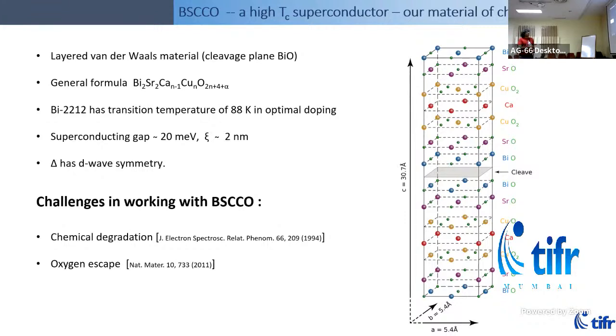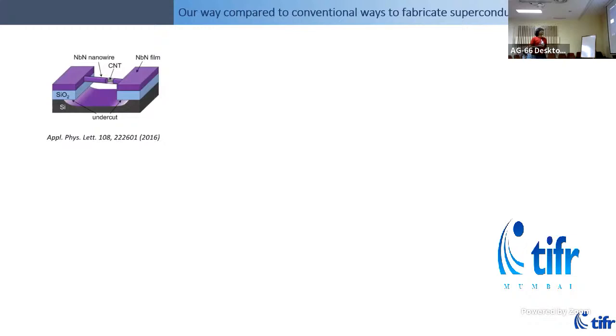And one of the prominent degradation mechanisms is oxygen escape. So in these copper oxide planes, which is where the superconductivity lives, oxygen leaves these sites, and you get vacancies, and then the material basically becomes a ceramic. And an interesting anecdote is that, because I had no experience working with BSCCO, we learned lots of things. Even to store these crystals of BSCCO over the months of different kinds of experiments, the mother crystal is stored at 77 Kelvin to prevent it from degrading. These are all things that we learned while working.